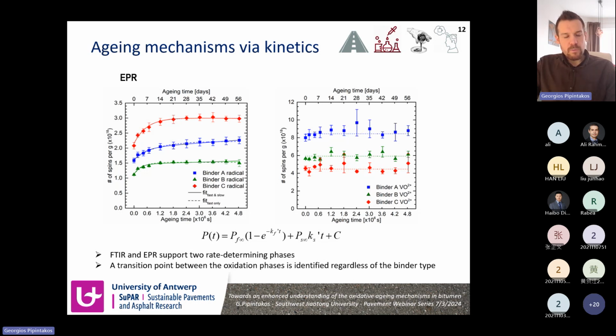So also from EPR, we were able to support two rate determining phases, regardless of the bitumen type, distillation, presence of wax or not, so waxy binders or not. So the two techniques together, FTIR and EPR, were able to support the hypothesis of two rate determining phases, and also to prove that indeed we can talk about formation of organic carbon center radicals, which were captured one of the first times that was reported in such extent with kinetics.